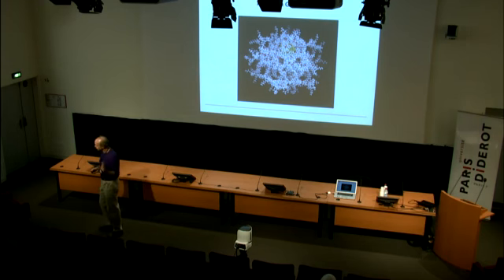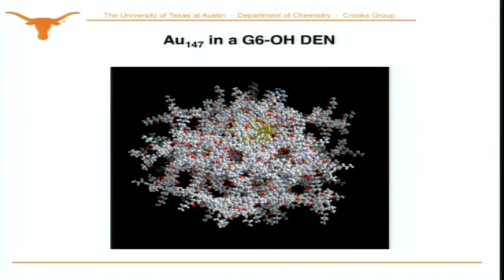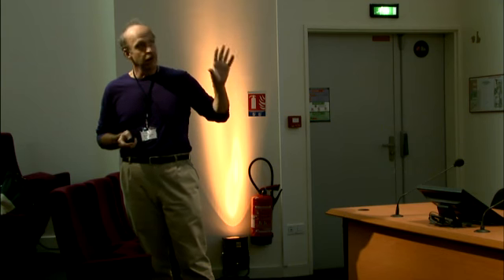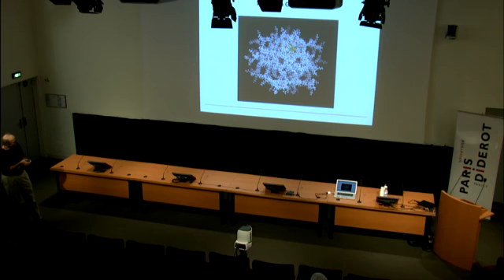Okay, this is just a cartoon. It's just to show you that the dendrimers are not as regular as that two-dimensional projection showed. But it's also to show you this is a 147 atom gold particle inside a bigger, generation 6 dendrimer. This dendrimer is terminated with hydroxyl groups, and I think for everything I'll talk about today, the peripheral groups are hydroxyl groups. That's important. It's better to be hydroxyl groups than primary amines because primary amines coordinate metal ions too.